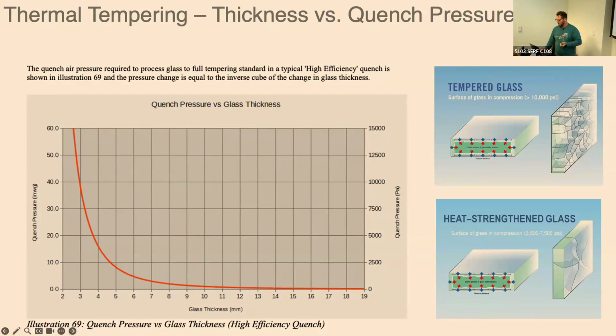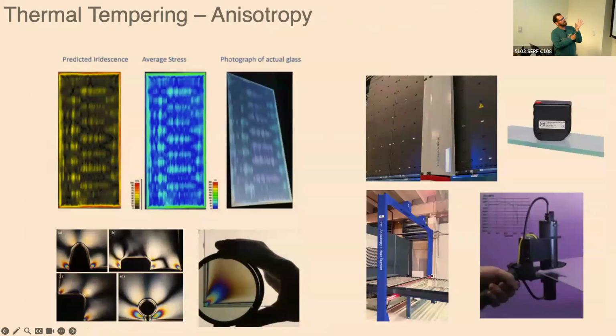In thermal tempering, these are polarized light scans of long rectangular glass, and also things with holes in them and corners. John has a bunch of equations; I just have color charts to give you a sense of where the problems may be. You're looking at the polarized light, at differential stresses in your glass pieces. Thermal tempering tends to be done at the bulk level, in the middle of the glass. You're tuning a stress profile and a breakage pattern in the middle.